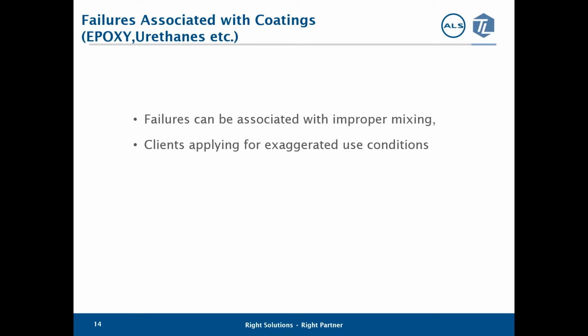For coatings, there are a couple of additional factors to consider. Improper mixing and application of the coating test slides can be associated with failures, in addition to clients applying for exaggerated use conditions. The potential issues associated with improper mixing are self-explanatory, but the subject of clients applying for exaggerated use conditions may not be.